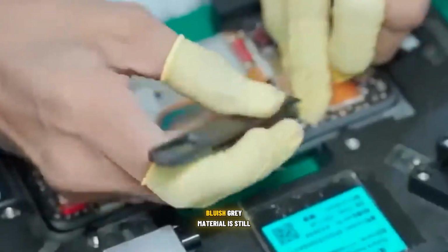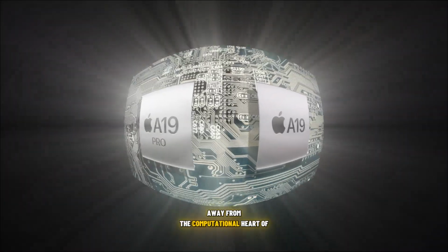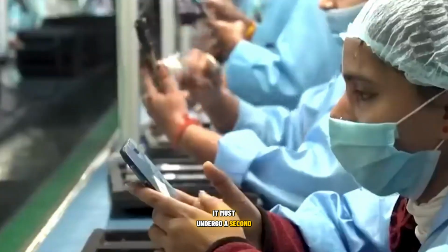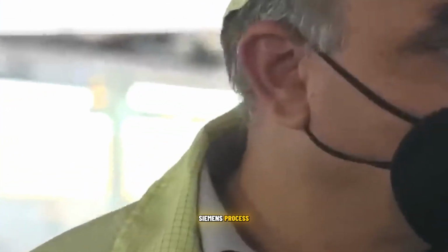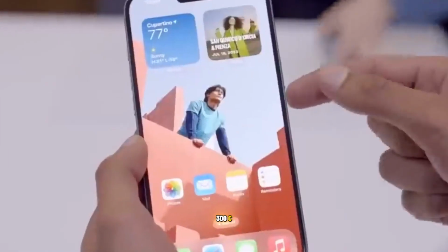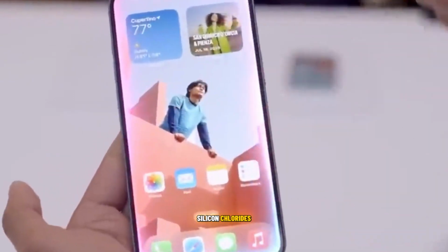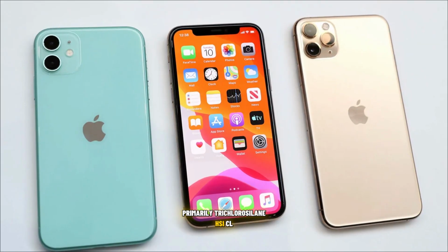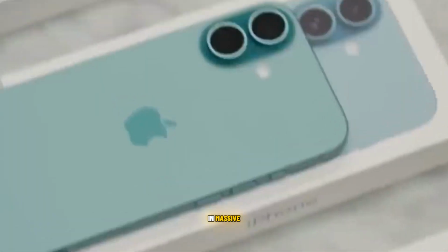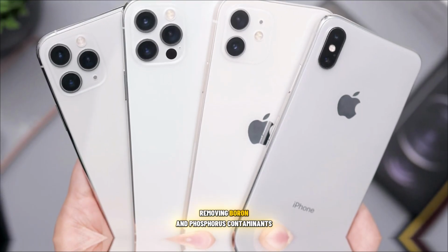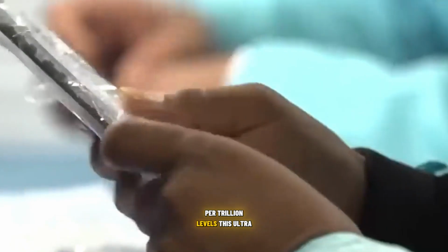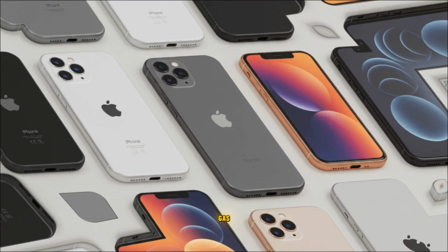But this rough, bluish-gray material is still light years away from the computational heart of a chip. It must undergo a second, even more precise purification, the Siemens process. The metallurgical silicon is ground into a fine powder and reacted with hydrochloric acid in a fluidized bed reactor, transforming it into a cocktail of silicon chlorides, primarily trichlorosilane, HSiCl3. This gas is then distilled in massive 80-foot-tall distillation columns, a process repeated multiple times to achieve an unparalleled level of purity. Removing boron and phosphorus contaminants to parts per trillion levels,